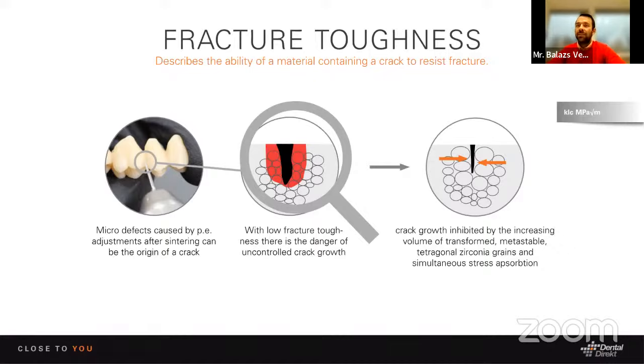The material, the zirconia, it's nothing new, it will have micro defects, micro cracks. It's a natural thing. Sometimes you have to grind your zirconia crowns in the practice, sometimes you have to grind contact points, some adjustment. This is a normal thing, and it also happens in the dental laboratory. So when you don't have to touch a crown in your dental practice, you never know what was done in the laboratory before. Therefore, it's really important that we speak about the fracture toughness.